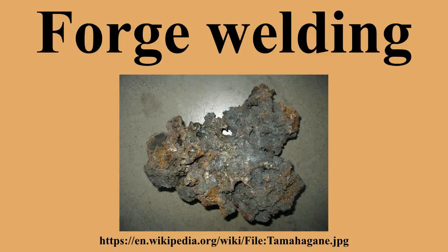Due to the poor quality of ancient metals, it was commonly employed in making composite steels, by joining high-carbon steel, steels that would resist deformation but break easily, with low-carbon steels which resist fracture but bend too easily, creating an object with greater toughness and strength than could be produced with a single alloy. This method of pattern welding first appeared around 700 BC, and was primarily used for making weapons such as swords, with the most widely known examples being Damascus, Japanese, and Merovingian swords.